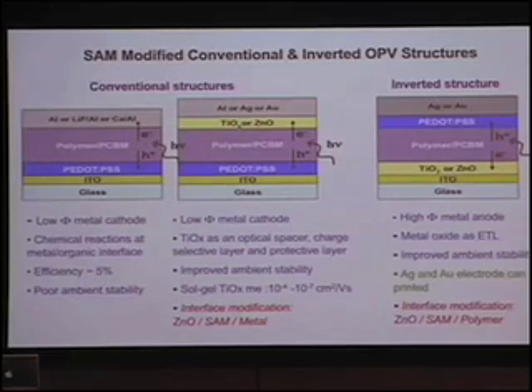So I would like to utilize a couple cases to show you. First one is based on so-called conventional device structures for polymer-based solar cells. You basically utilize ITO as an anode, and on top of that you have a low work function metal as a cathode. So you basically have a blend system with a donor and acceptor, like C60, blended together to create a bulk heterojunction.